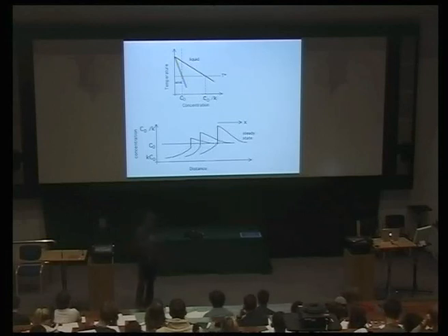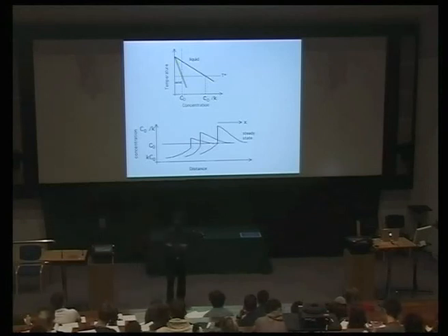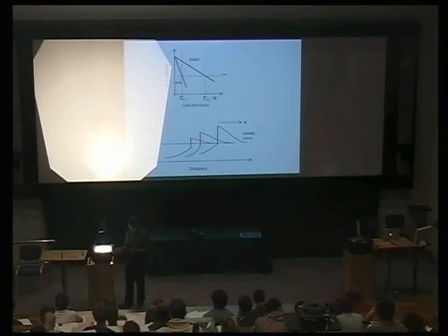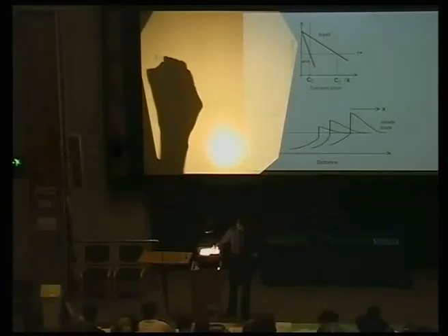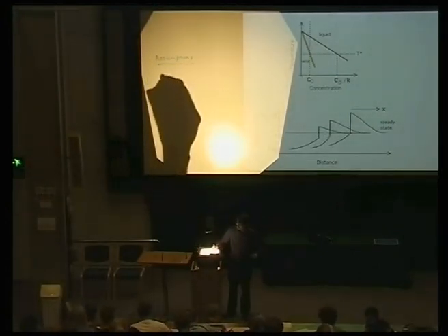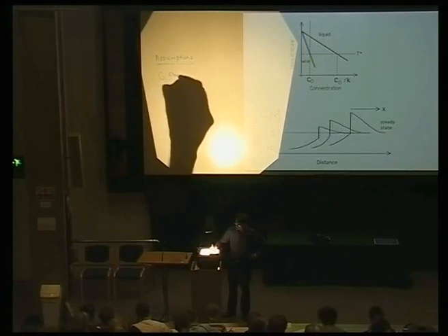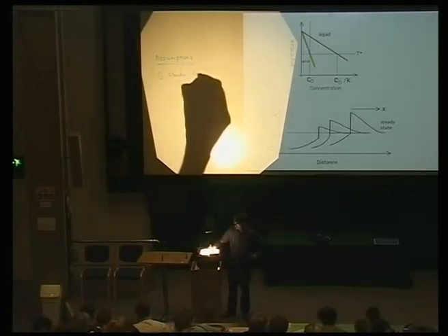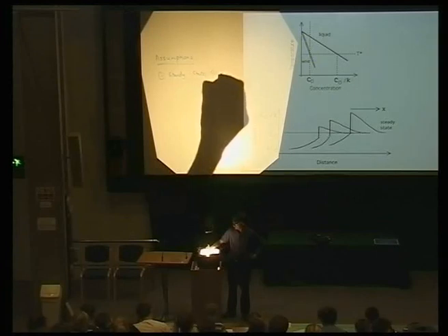Okay? So this lecture today is an introduction to solidification theory, and you should realize the approximations that I've made in deriving this equation. First of all, I've assumed steady state solidification. Okay? So these are the assumptions. Steady state solidification.